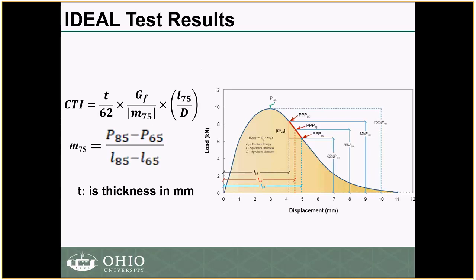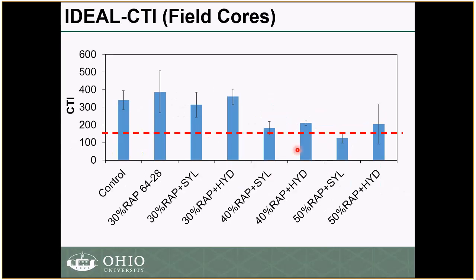This procedure was developed by Dr. Fuji from TTI, basically as part of an NCHRP IDEAL study. And basically that depends on the fracture energy and also the slope of the post-peak. This test is conducted in the same way as an IDEAL test. The only thing is that you have to monitor loads and deformation, and basically you need to record them throughout the test.